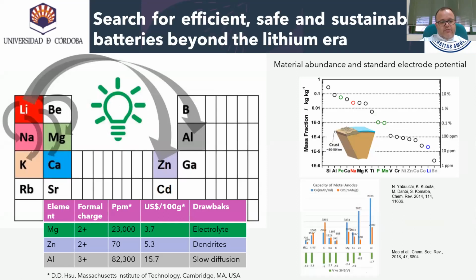among the metal anodes, the high capacity, low reduction potential, and most importantly, dendrite-free deposition with 100% of Coulombic efficiency, in some electrolytes make magnesium metal an ideal anode. The abundance in the earth crust and the price per metric ton make magnesium very attractive versus other divalent or trivalent metals such as zinc or aluminum. But the divalent nature of magnesium makes the diffusion of magnesium more sluggish than monovalent cations such as lithium.